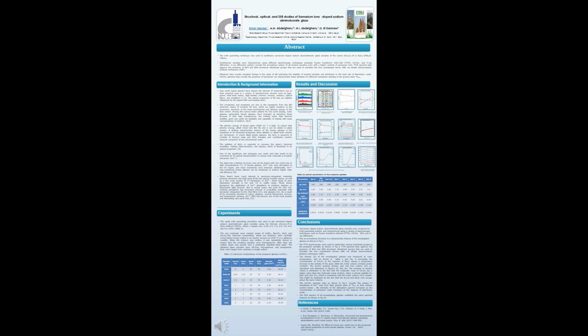For the current study, synthesized samples were characterized using different spectroscopic techniques, including Fourier transform infrared, UV/Vis, and X-ray diffraction. The X-ray diffraction pattern reveals the amorphous nature of all studied samples. The results of FTIR and density show that by adding samarium oxide at the expense of aluminum oxide, there is almost no change in the structure of the glass.